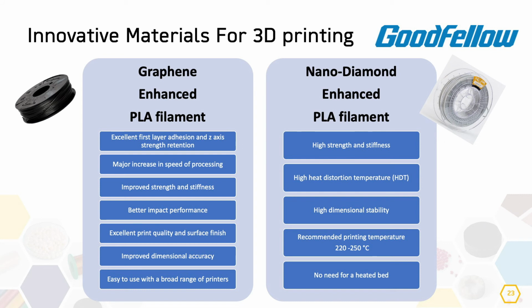While having nanodiamonds, which in this case are spherical nanodiamonds, enhancing the PLA filaments, we also have higher thermal conductivity, and what is most important is that the nanodiamonds are less abrasive than the irregular shape fillers that are used commercially. So this leads to lower nozzle wear, and also offers enhanced printing speeds. Because as we all know, diamond, and especially nanodiamond, has lubrication properties.